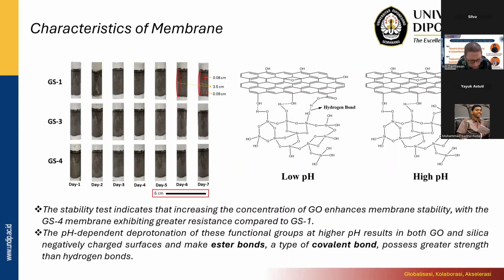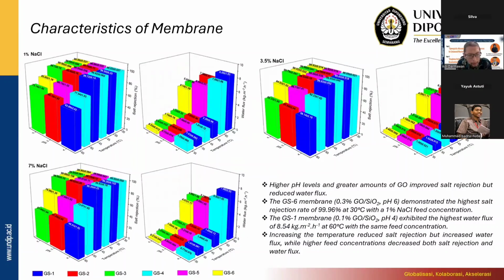Okay. After that, this is not the characterization. This is the performance of the membrane. It's quite the same: close to 100% for the salt rejection, but the water flux is close to silica. Yeah, close to silica, around 4 until 8. Much lower compared to the GO-PVA membrane.